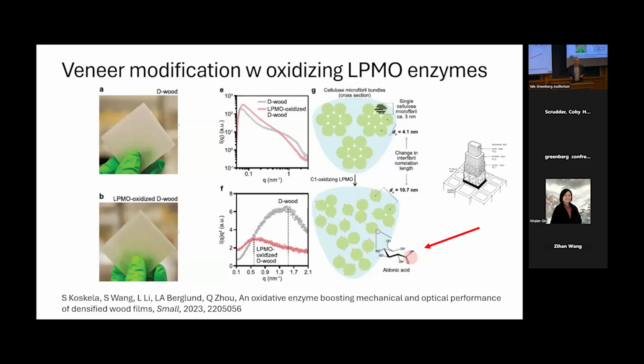If you then use oxidation, that's a different procedure where you remove essentially all of the lignin, and the idea is to separate the microfibrils. This is data from small-angle X-ray scattering, and this is the interpretation. The microfibrils are embedded in lignin and hemicelluloses, and in the initial state they are close together, with a distance between them of 4 nanometers.